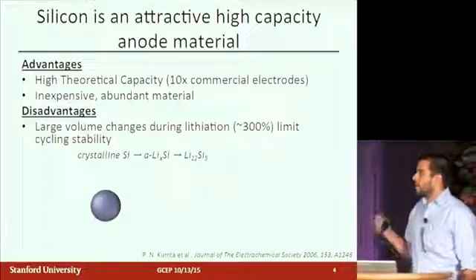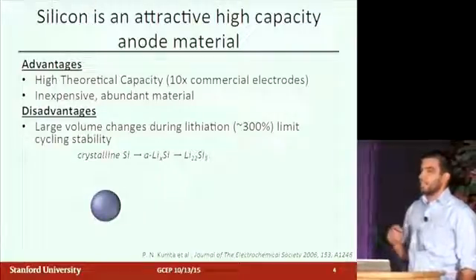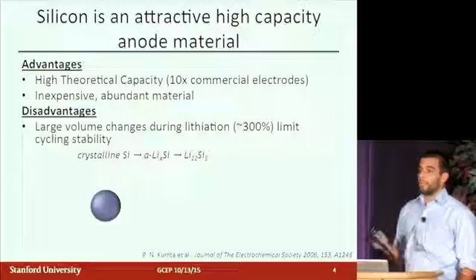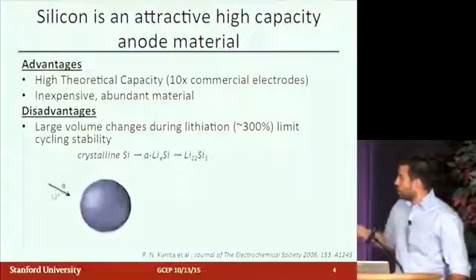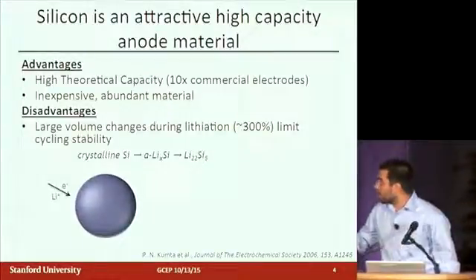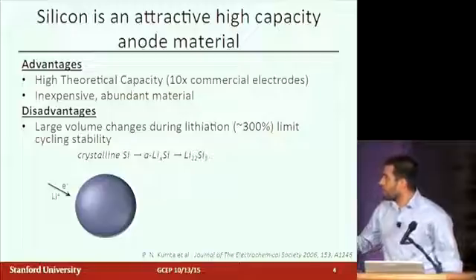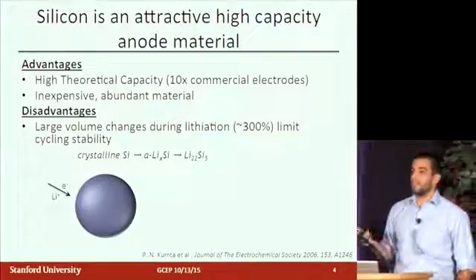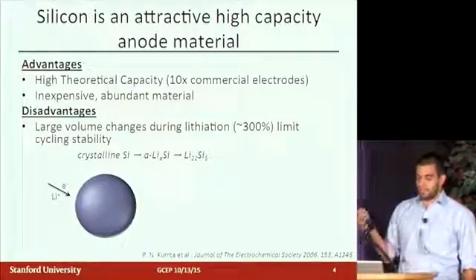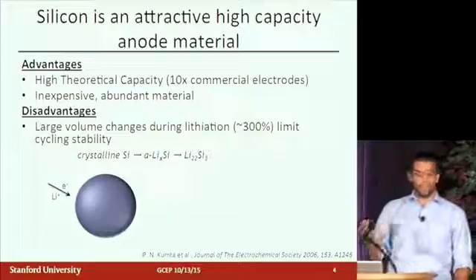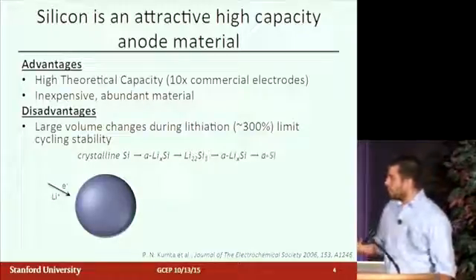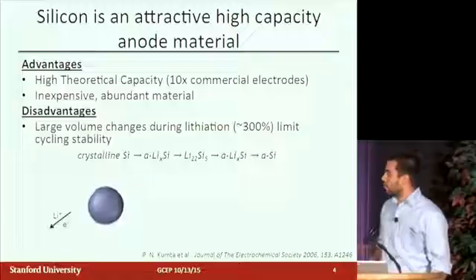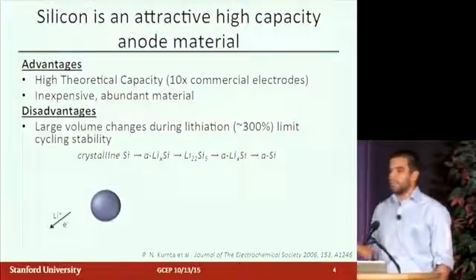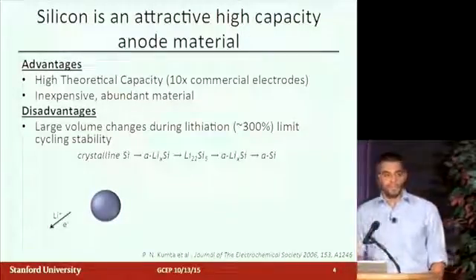The problem, and the reason we're not using it today, is that it undergoes huge volume expansion when it charges with lithium. You'll see there's a lithium phase, 4.4 lithium atoms for every 1 silicon atom, which results in about 300% volume increase. And then when you delithiate, you go back through to amorphous silicon, and it shrinks. But silicon's not a balloon. It doesn't just blow up elastically.